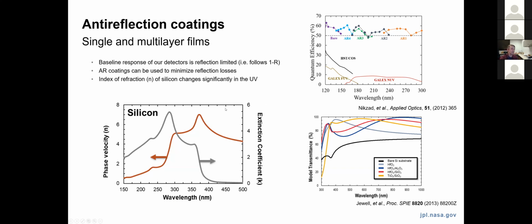What that ends up meaning is that in certain bands, we can achieve very high external quantum efficiencies, in this case, by appropriate choice of AR coating, but you may have to mix and match as you move through the far ultraviolet, especially. And so this plot on the upper right here is showing a series of delta doped CCDs that were fabricated for an instrument concept that was being led by Chris Martin at Caltech that wanted to cover the far UV over multiple bands on multiple devices, essentially.